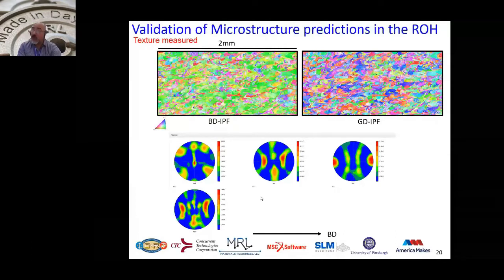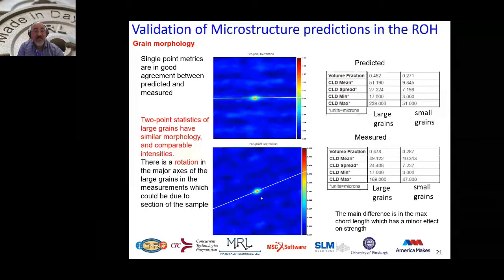And when we wanted to talk about morphology, we use our higher order statistics, and those allow us to use two-point correlation to compare predicted as well as measured morphology of the grains. And then we use a modified line intercept method, we call the chord length distribution, that you will find both of them in the earlier paper. What you can see, we were pretty close in the morphology as defined by the two-point correlations. We have some tilt that could be due to the cutting of the samples, but the volume fraction as well as the morphology as identified with the two-point correlation, we're pretty close.